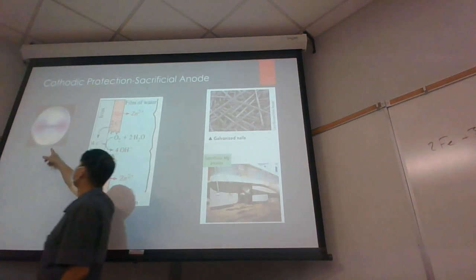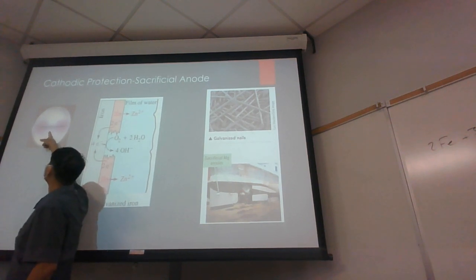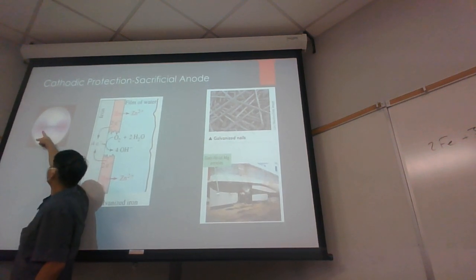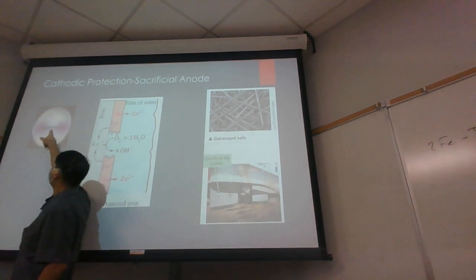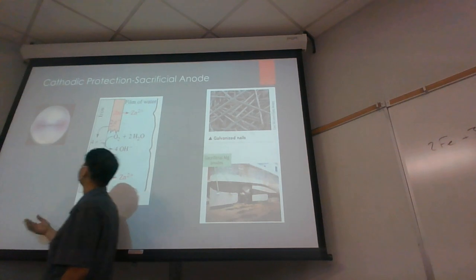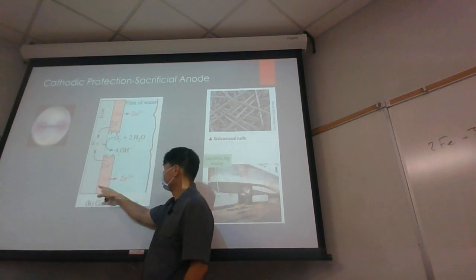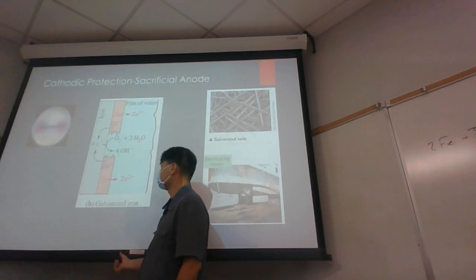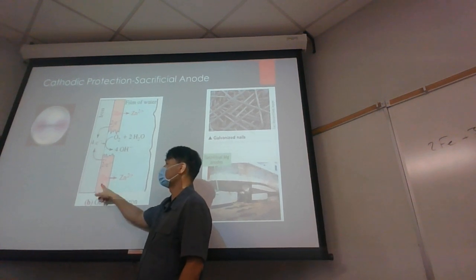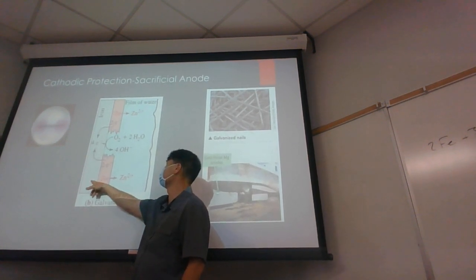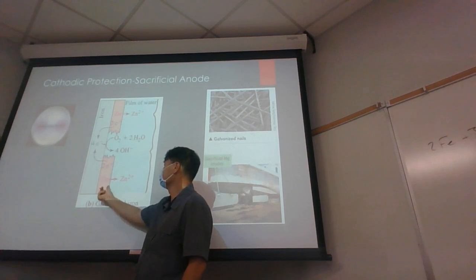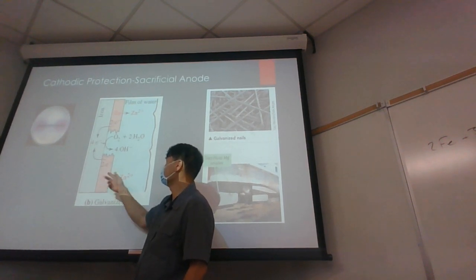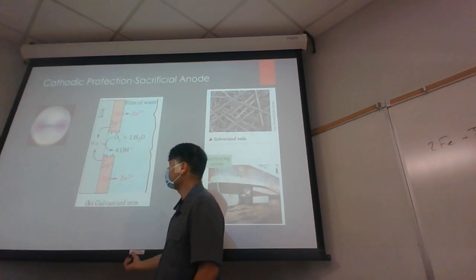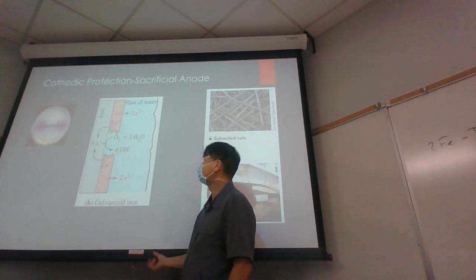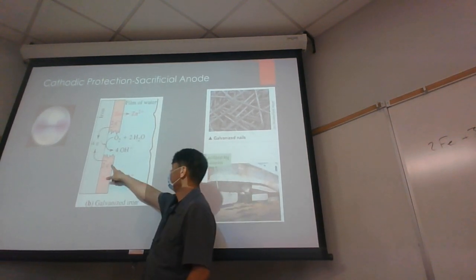So you can see some zinc foil wrapped around here. And so what that means is that the iron turns out to be the cathode. You can see the hydroxide being generated there, and the zinc is the new anode. And so we call it sacrificial anode because the anode is what gets oxidized, and zinc is easy to oxidize, and we'll replace the zinc instead of the iron. Now, the zinc is not a structural material, so the nail is going to retain its structural integrity, whereas the zinc will be eaten away.